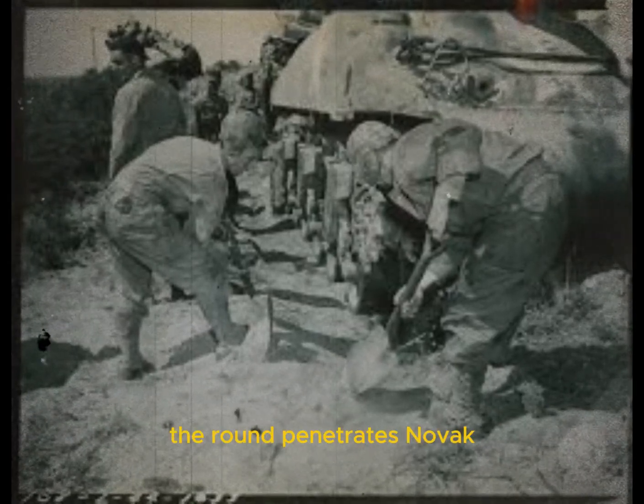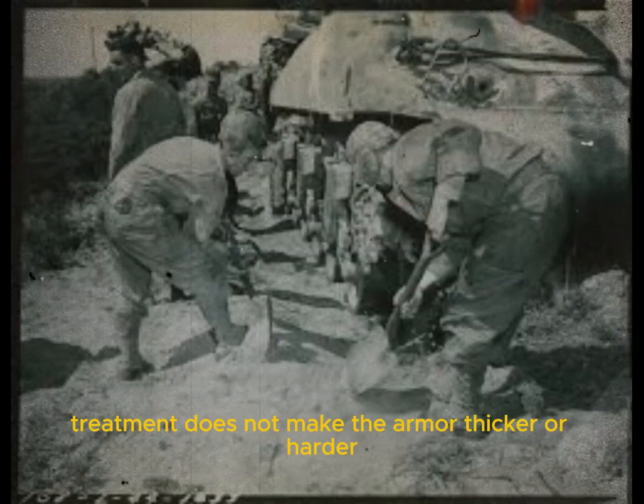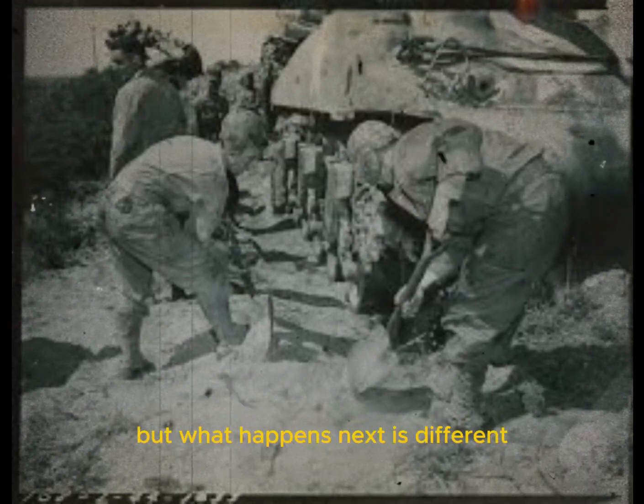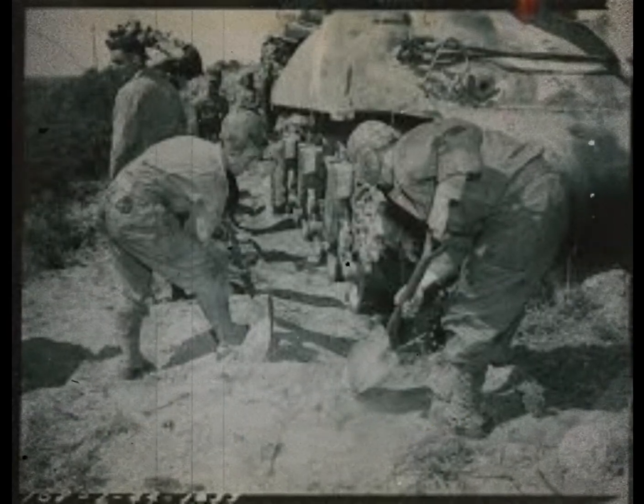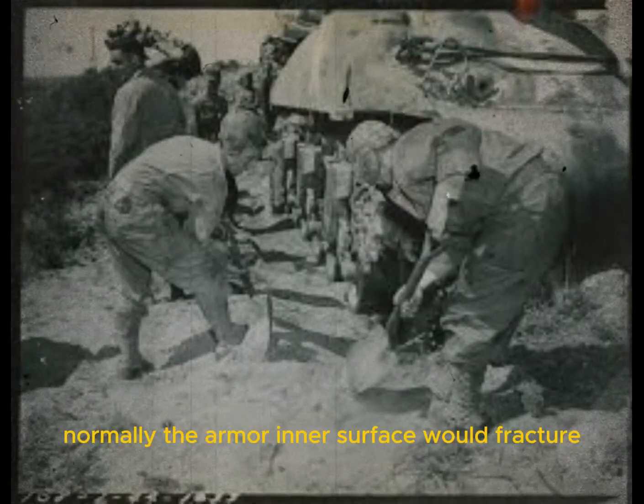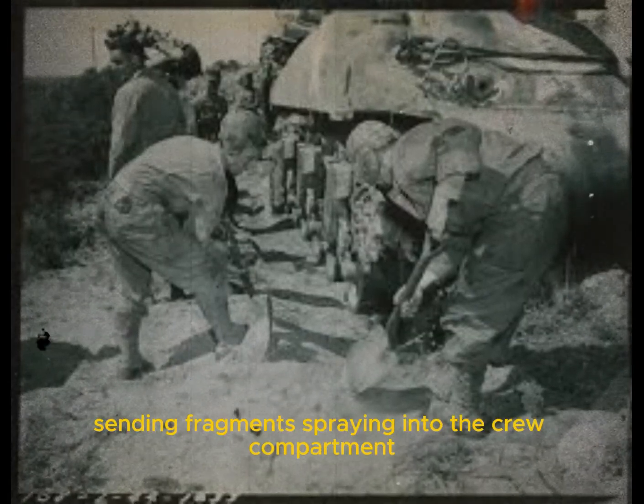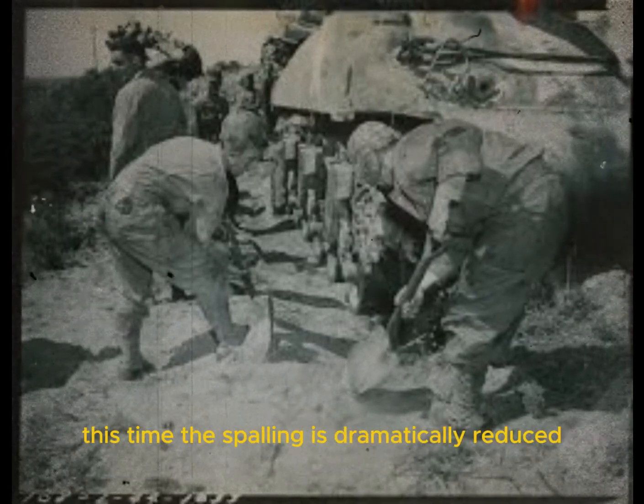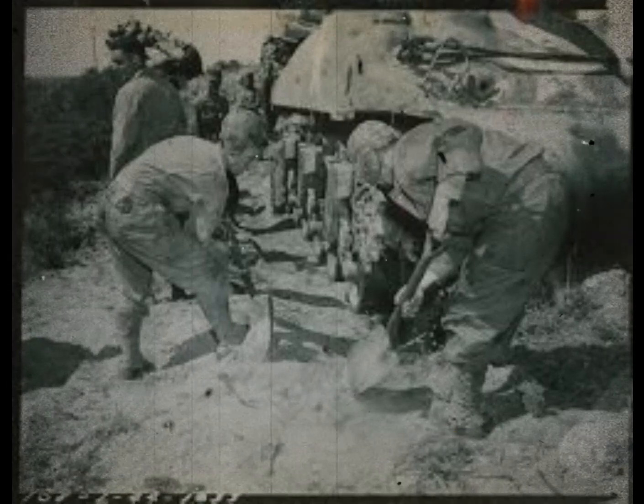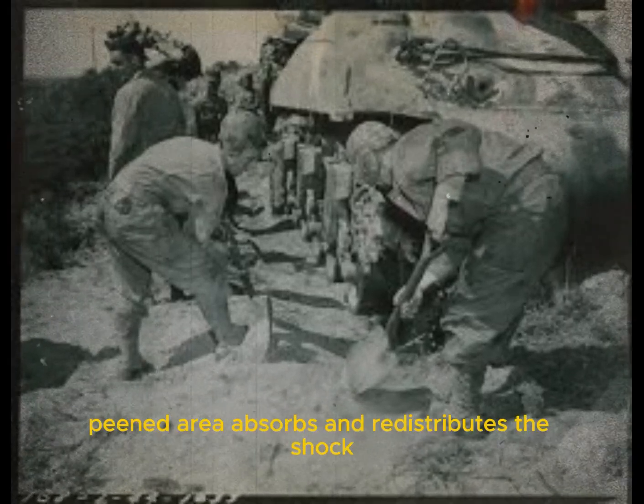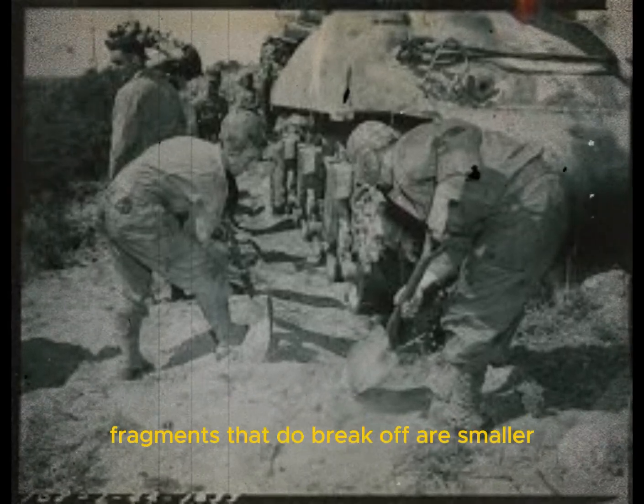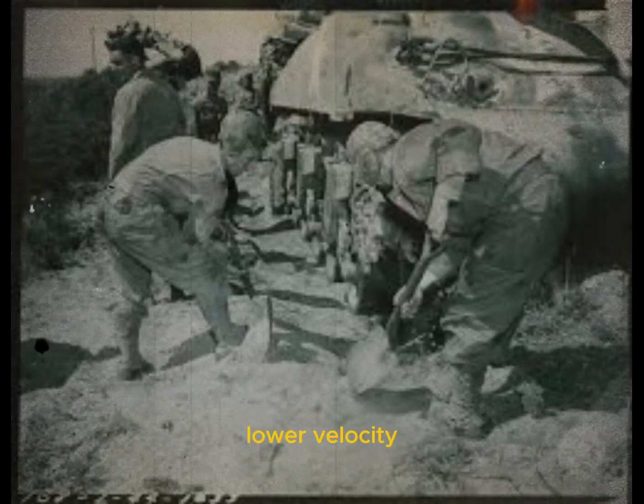The round penetrates. Novak's treatment does not make the armor thicker or harder, but what happens next is different. Normally, the armor inner surface would fracture, sending fragments spraying into the crew compartment. This time, the spalling is dramatically reduced. The weld-peened area absorbs and redistributes the shock. Fragments that do break off are smaller, lower velocity.